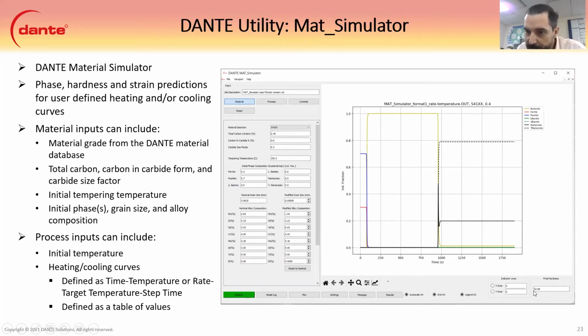The final hardness was predicted right down here. We give the final hardness based on the metallurgical phase. It's that mixture law that we were talking about earlier. And that came out to be about 52 HRC. You can change it to Vickers, I believe, in the inputs as well.